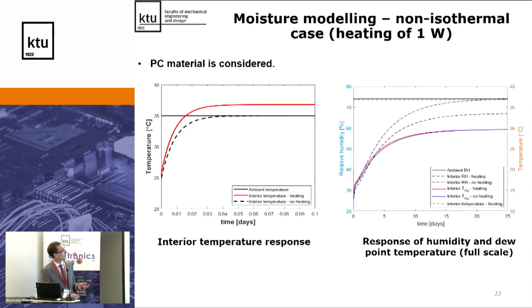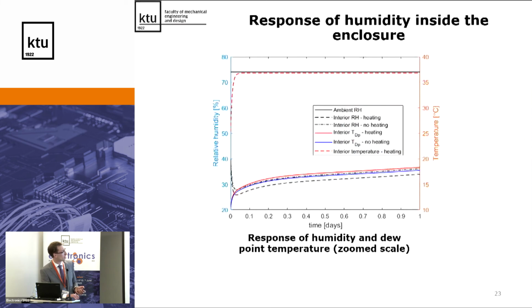And then we applied heating. Only PC material is considered, just to show what difference we get. And of course, when we have a heating of 1 watt, we have a lower relative humidity compared to no heating. And then, of course, in case of heating, we have a bit higher dew point temperature. And here I show the zoom scale that is slightly higher, because temperature increases the diffusion coefficient. The diffusion coefficient is temperature dependent.